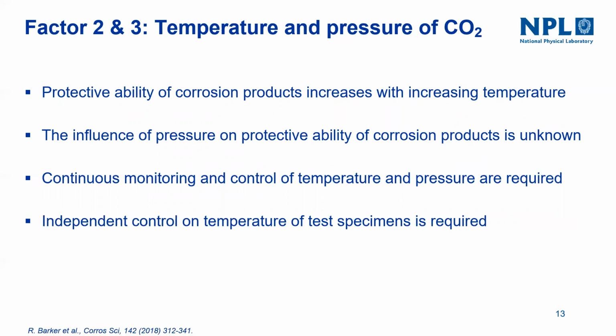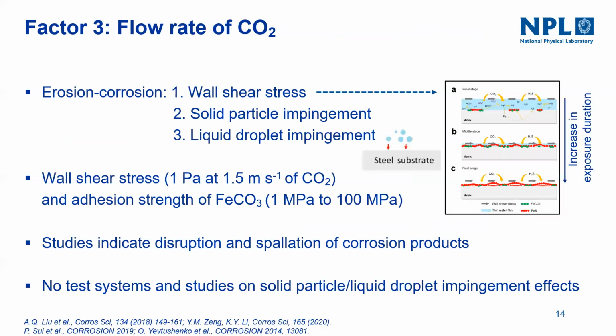This is important because the pipeline surface has a temperature influence from the surrounding atmosphere, and there could be a temperature change close to the surface that can have an influence. So independent control of temperature is very much essential, but none of the experimental designs have managed to build that kind of experimental setup. The third one is the flow rate.